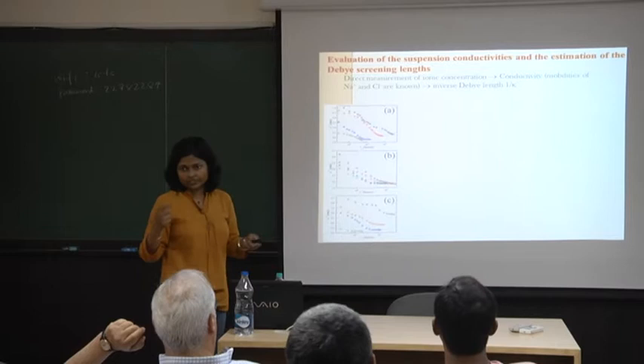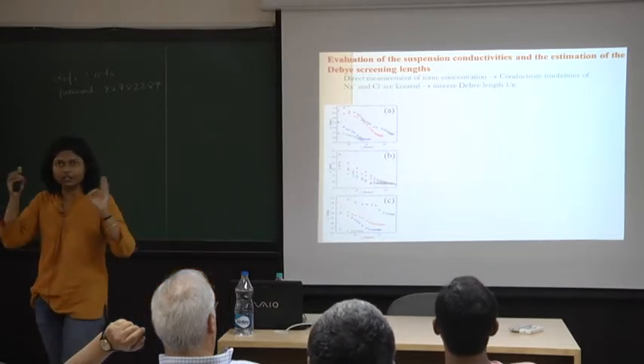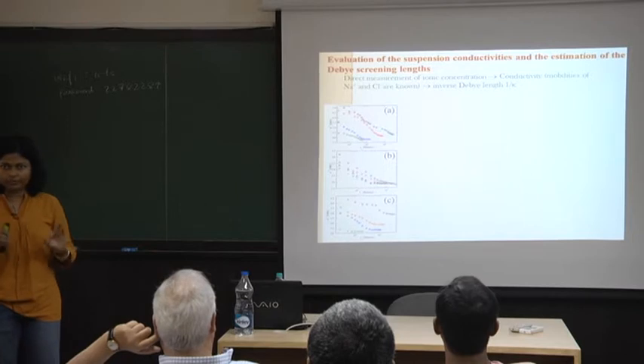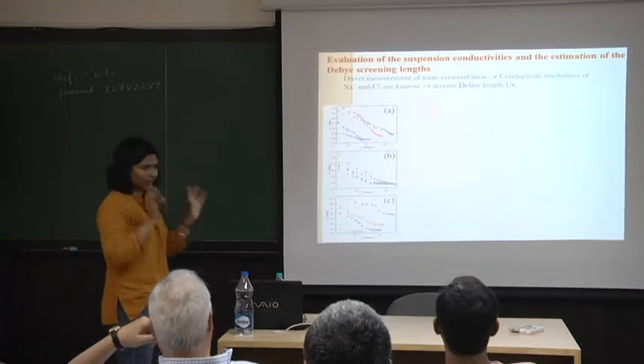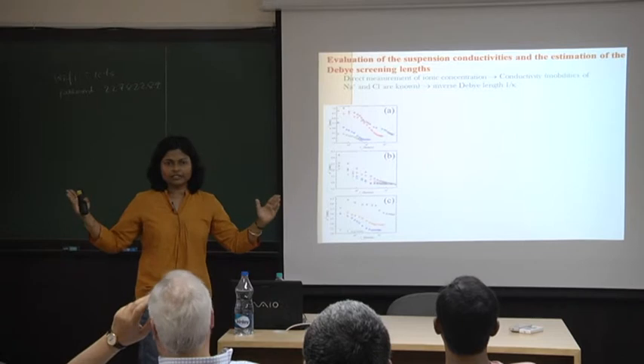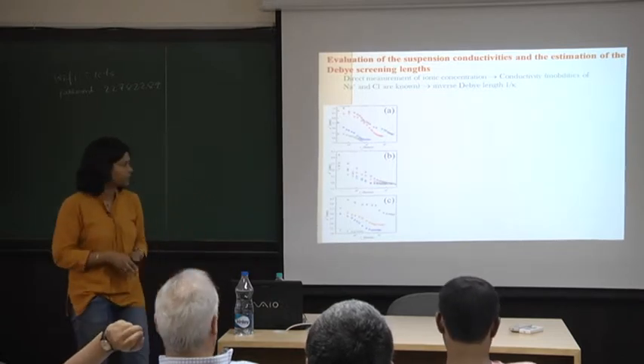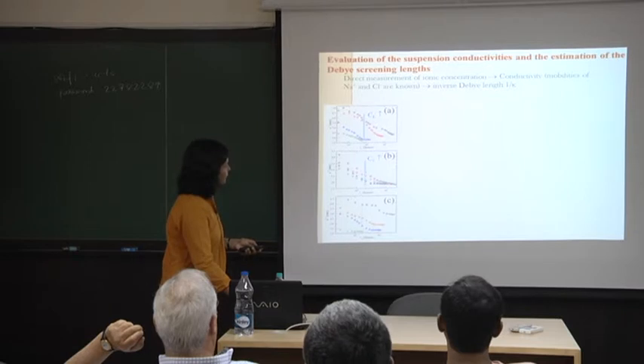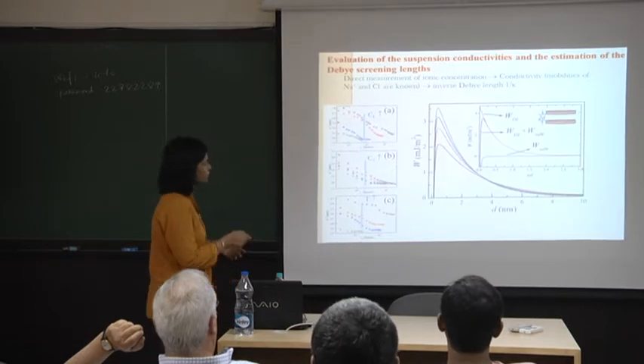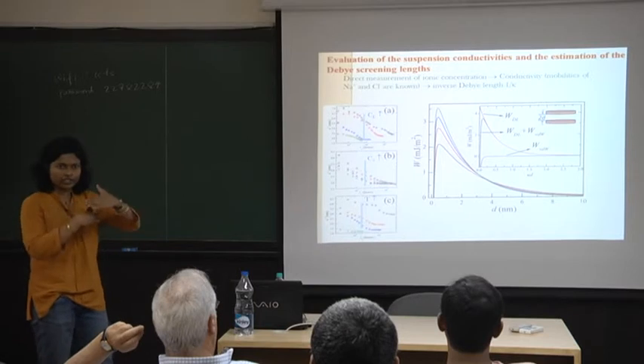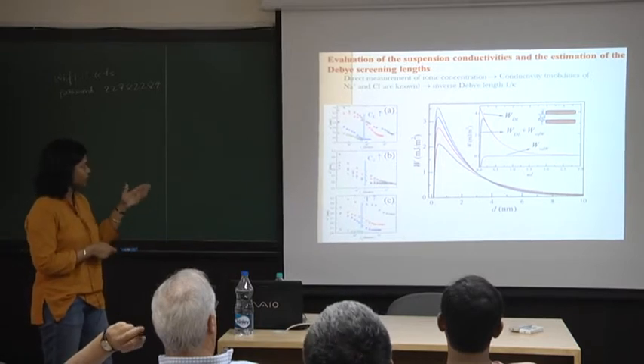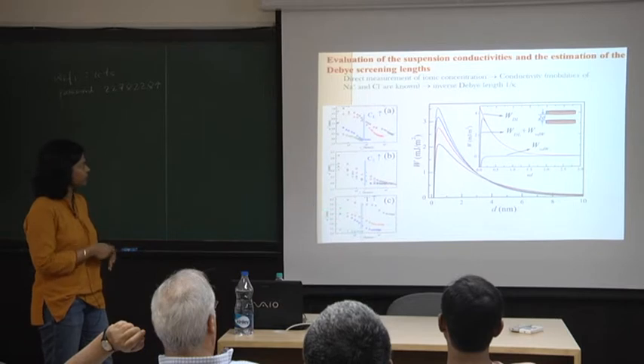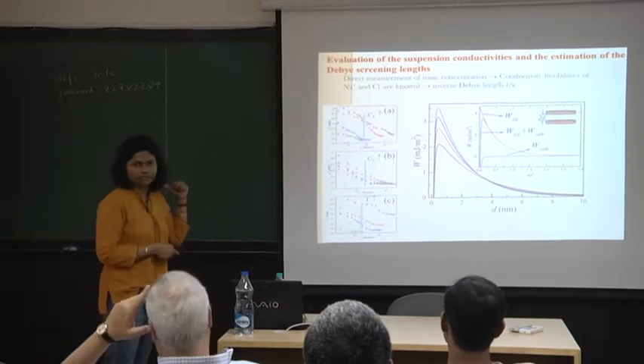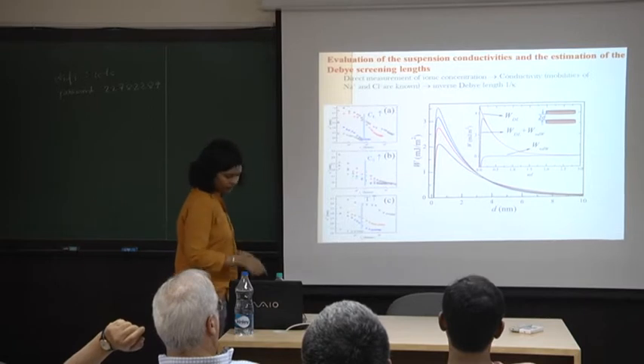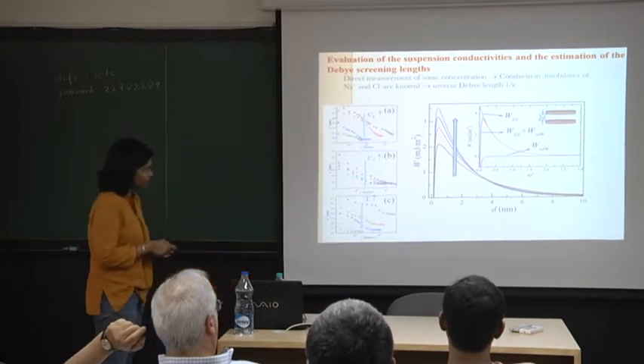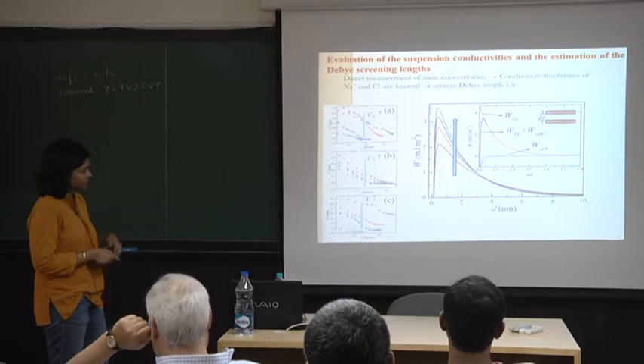Using all the values that we have from the sodium ion concentration, we can plug them into a DLVO model, which accounts for the van der Waals interaction between plates as well as the screened electrostatic repulsion between the plates. We calculated the potential between two plates approaching each other parallelly. For that we needed the Debye length, which we calculated using our sodium ion concentrations that I showed you earlier. So this is the interparticle potential versus distance of separation.